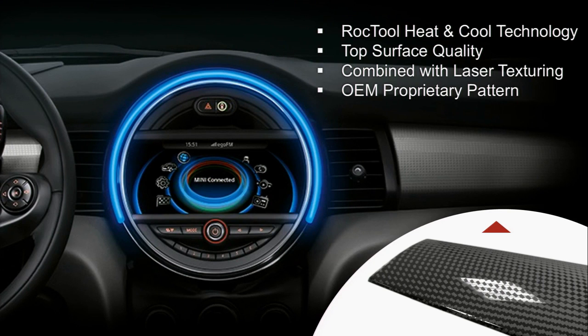Those are also another example of a texture. So just to explain, there's part without. It's in French. In the back it says sans, so without. And we push the limits to include directly holograms on the tool surface. So conventionally, you almost don't pick them up. But when you turn on the induction, that turns them on. And you can see them like some kind of an image. So that's interesting for maybe some applications for protecting the application itself, making sure that it's not a copy directly from the mold itself. And the interesting thing I find is if you put your finger over it, you can barely feel anything. It's amazing.